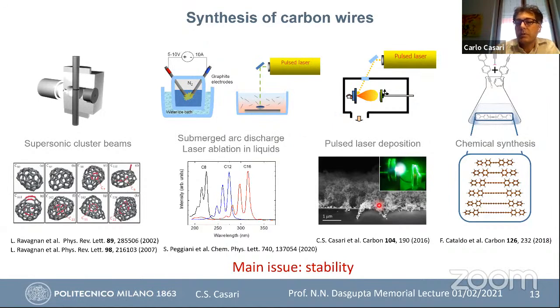Another possibility is pulsed laser deposition in the presence of a background gas. Or by collaborations, we have the possibility to have this kind of system by chemical synthesis, which is very good in finely controlling the termination. Of course, one problem for these systems, that I also mentioned when talking about the wire inside carbon nanotubes, is the stability, because these systems are mainly affected by degradation. So the stability is very important if you want to then test a material and its properties for possible applications.